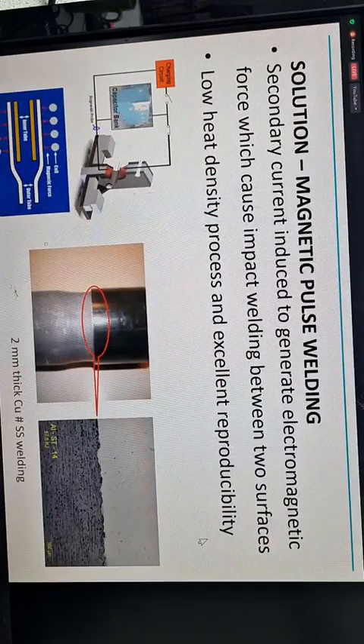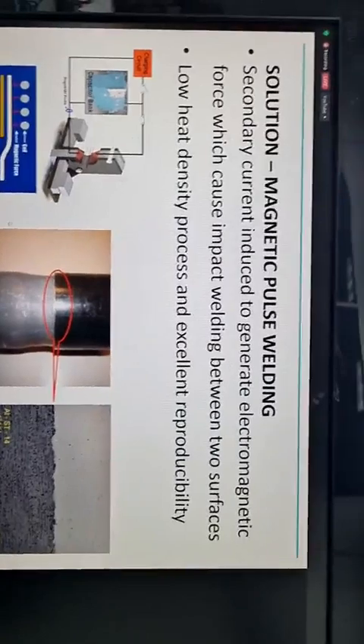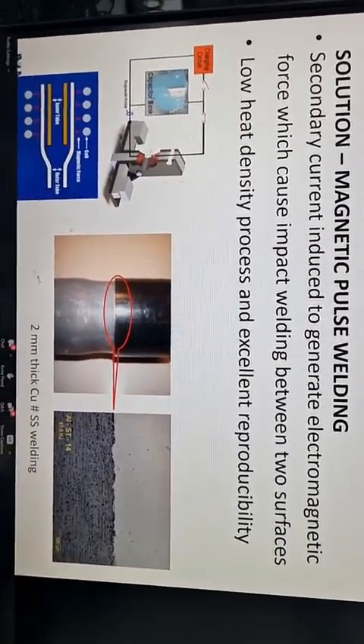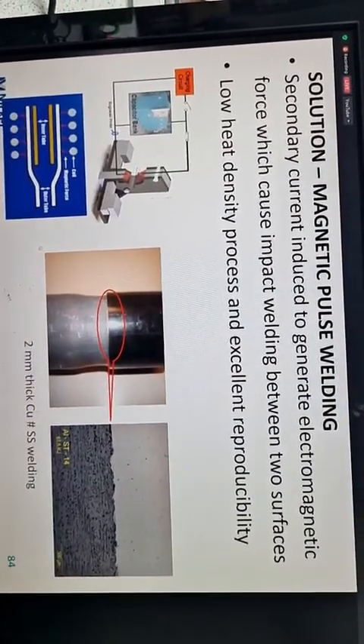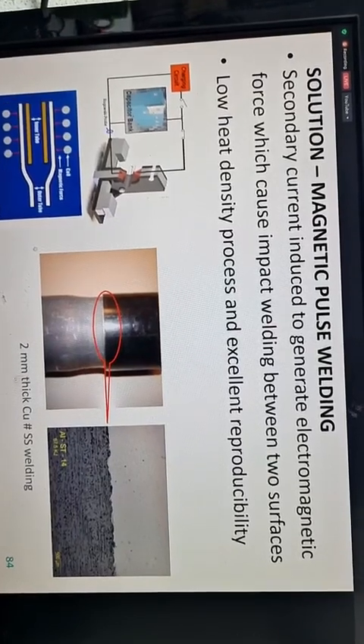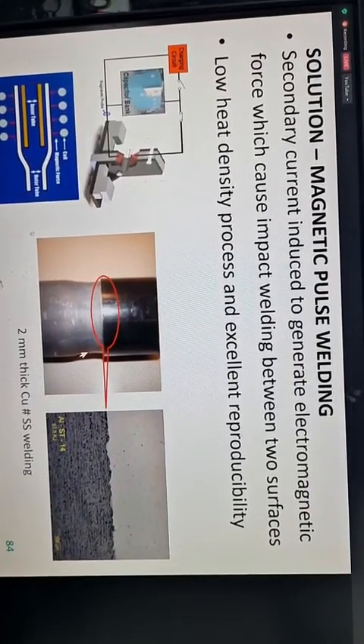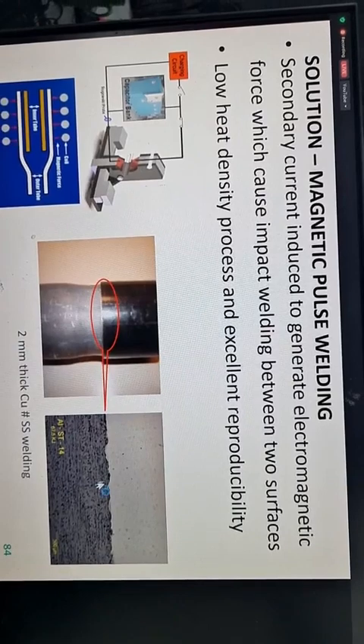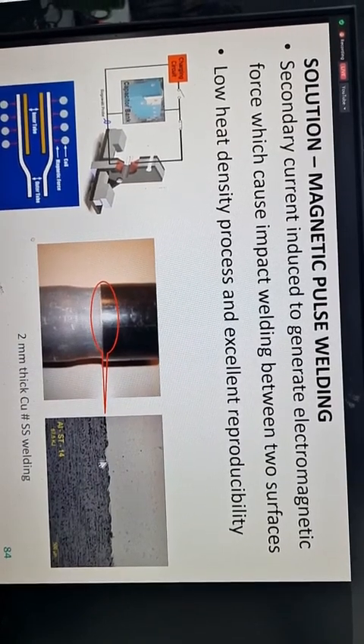And this is an interesting technique, rather a process, known as magnetic pulse welding, which is being used when you have small intricate shapes having dissimilar metals. So the photo which I have shown is a 2 mm thick copper to stainless steel weld, and you can see how beautifully it has got joined